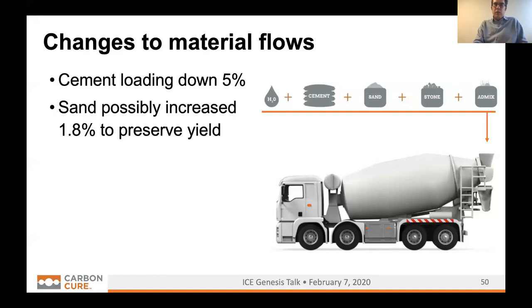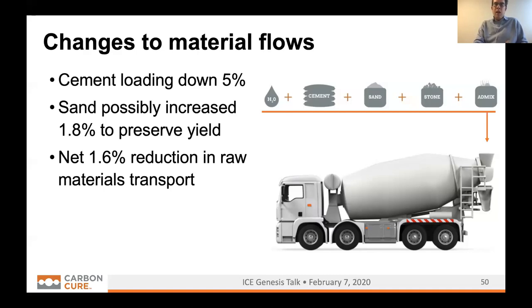If you look at the material flows, this producer can take out 5% of the cement. That reduces the volume of the mix, so it's possible that they may increase the sand slightly. Not every producer does this, but it's possible that they will. If you did both of those things, because the sand is closer than the cement, you end up reducing the raw materials transportation emissions. And these steps on the transport avoid almost 300 grams of CO2 per cubic meter of